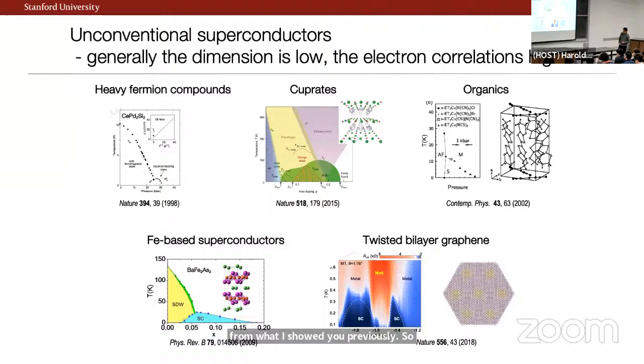Common features of these are that they're generally low-dimensional, quasi-two-dimensional states or explicitly 2D situations. Electron-electron interactions are very strong compared to what you would see in a typical metal or semiconductor. And they're often characterized by a dome of superconductivity as a function of a tuning parameter. It can be pressure, where you squeeze on the material, or it can be doping, where you chemically dope this as you would in a semiconductor. It's a little bit hard to see perhaps, but all of these cartoons or phase diagrams exhibit a dome of superconductivity in proximity to a correlated phase, often exhibiting some form of magnetism, antiferromagnetism, some density wave magnet, et cetera.